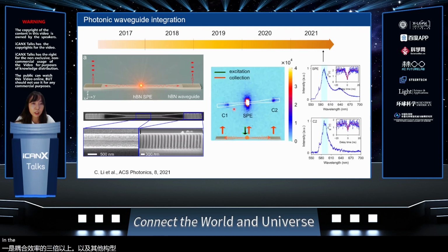In the PL map shown here, a single photon emitter, which we refer to as SPE, is positioned at the center of the hBN waveguide. This emission is coupled to the waveguide and scattered by grating couplers at the C1 and C2 positions. This data shows spectra collected directly from the SPE with an inset g2 correlation measurement. And we observed the same peak in the PL spectrum when we collect the emission from positions C1 and C2. The single photon characteristic is retained, as seen in this inset.